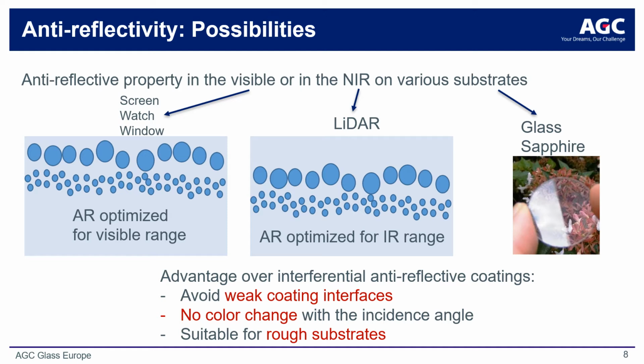Interferential AR coatings are an excellent solution for many applications, but an ion implantation surface treatment can offer advantages in two important ways. Firstly, AR coatings by ion implantation result in a high degree of angular color stability. You might notice sometimes that when viewing a coated optical surface from various angles, a rainbow effect can be observed. This is typical of traditional interferential coatings and often leads to undesirable cosmetic or functional effects. AR coatings by ion implantation, in contrast, appear the same to the viewer from any viewing angle.